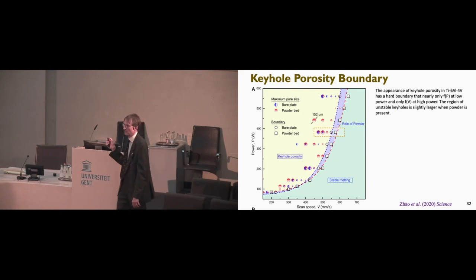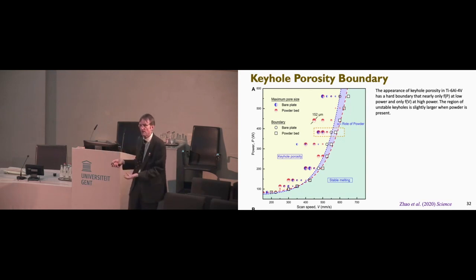So here's a diving into the details. Here's, I think, a key point. I showed you the movie of those bubbles forming and getting trapped, but what's the systematic approach to this? Kang Zhao, who was one of the team at APS, did a very large number of experiments at many different combinations of power and speed. What he found was that there was a very definite boundary between stable keyholes, no pores, and unstable keyholes forming porosity, and that this boundary was very reproducible. Moreover, you can do this on bare plate, but when you add powder, it does shift that boundary, but not very much. So powder plays a secondary role, which turns out to be the case in many different things.